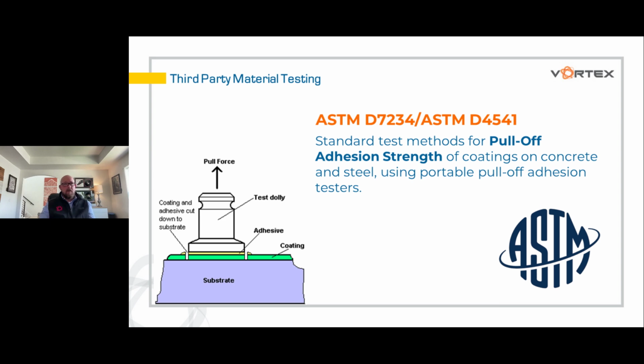Now, measuring PSI on concrete can be a little bit tricky. Of course, the pull strength is going to be inherent to the concrete's strength as well. So you can get substrate failure, but only get 150 to 200 PSI on your pull, and that still is a pass as far as we're concerned, as far as did that create the bond necessary.